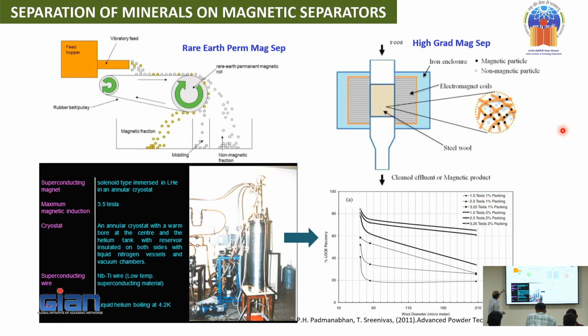So you can see here, this is a rare earth permanent magnet based separator. Now, when you go to this particular thing, as I was telling you, this is a high gradient magnetic separator, where the separating zone has a lot of wires. Because of this geometry, it will help in increasing the gradient. Therefore, the capture probability increases. Capture probability of finer size particles will increase.